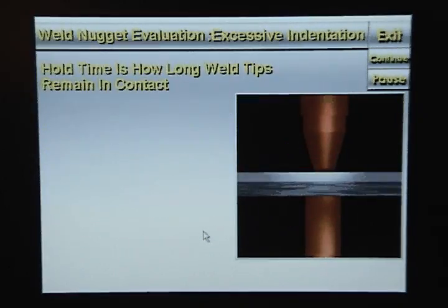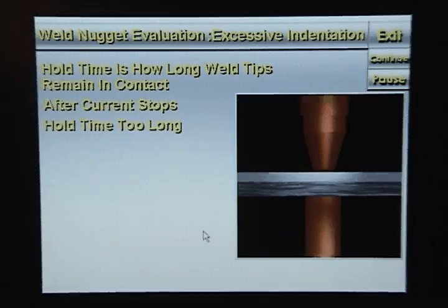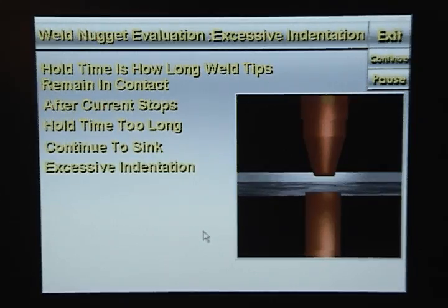Hold time is how long the weld tips remain in contact with the metal after current stops flowing. If the hold time is too long, the weld tips continue to sink into the metal, creating excessive indentation.